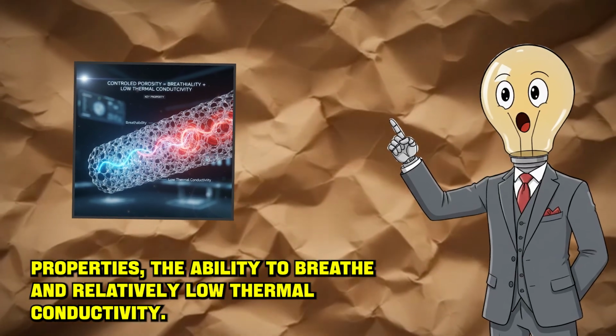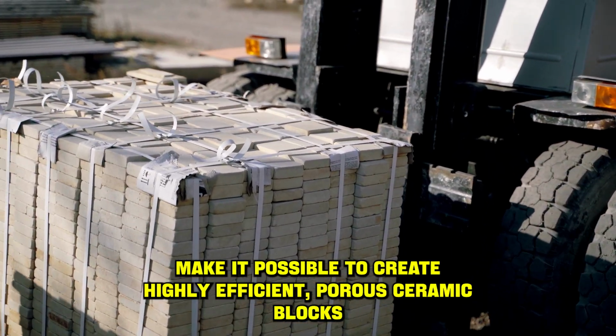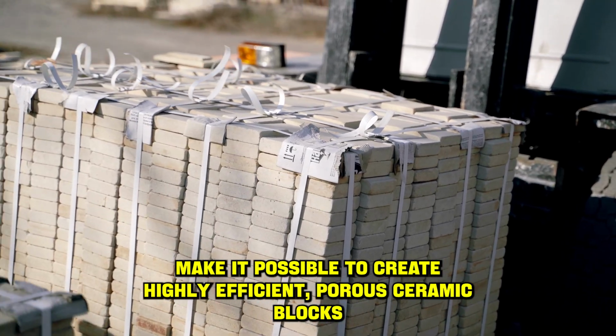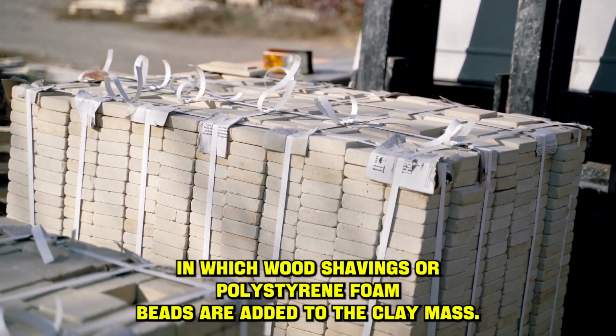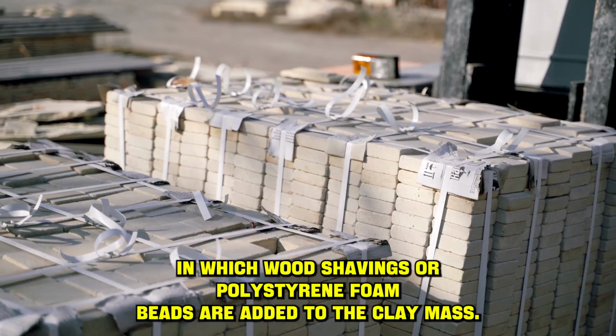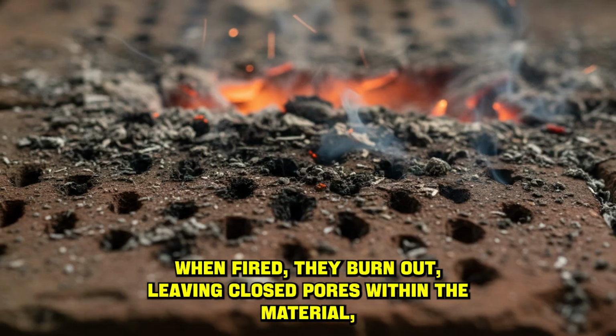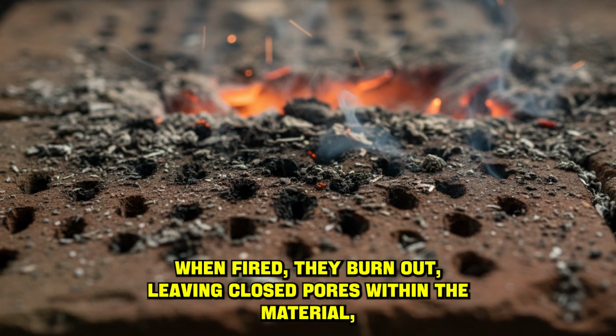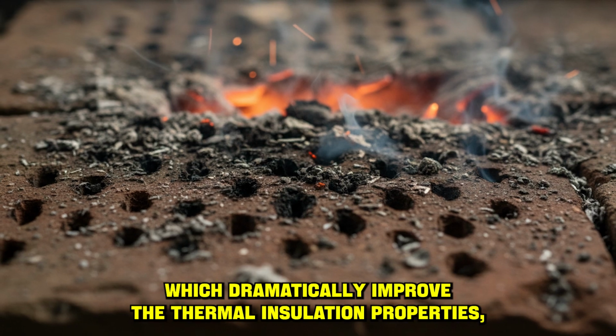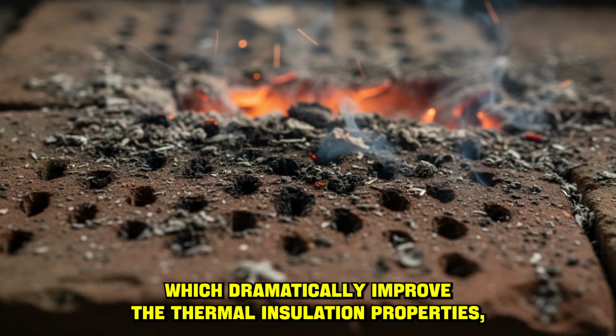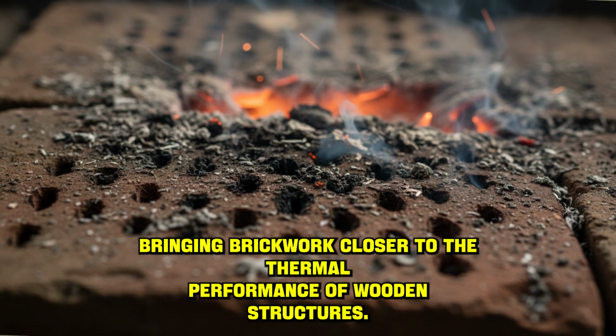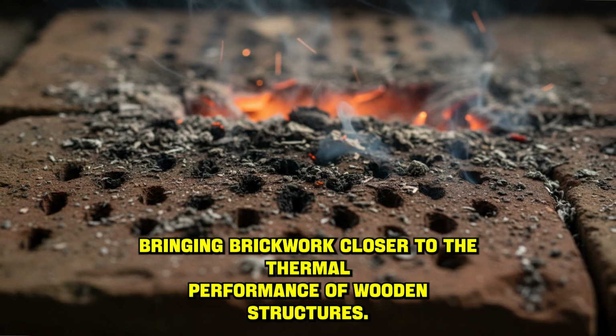low thermal conductivity. Modern technologies make it possible to create highly efficient porous ceramic blocks, in which wood shavings or polystyrene foam beads are added to the clay mass. When fired, they burn out, leaving closed pores within the material, which dramatically improve the thermal insulation properties, bringing brickwork closer to the thermal performance of wooden structures.